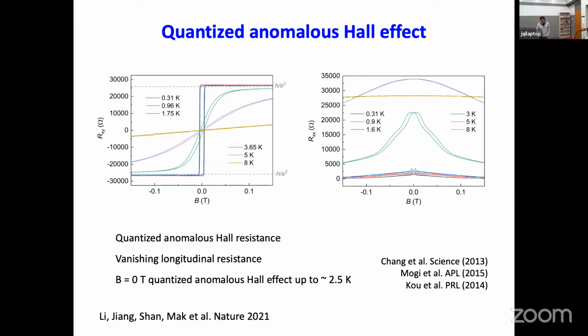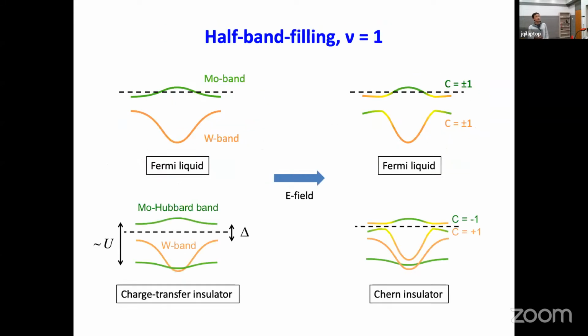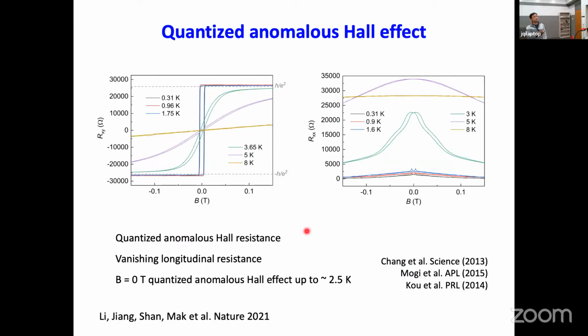So indeed, if we tune our system to just after band inversion, and then tune the filling factor to equal 1, you actually see that, boom, suddenly the Hall resistance gets quantized at zero magnetic field. This is the Hall resistance data on the left. At different temperatures, you can see that below about 2 Kelvin, the Hall resistance is nicely quantized to h over e squared. At the same time, the RXX data on the right goes to a very, very small value